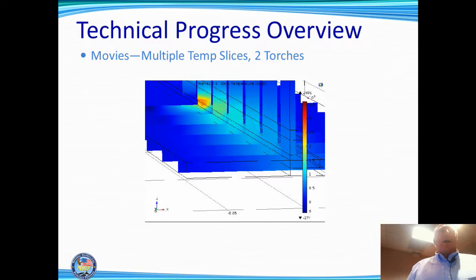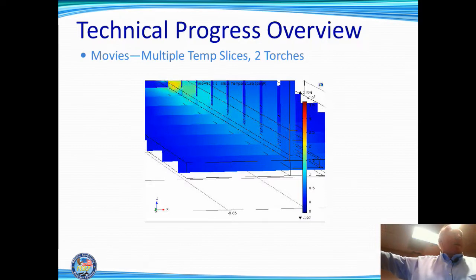So the fact that we have these models will help us a lot now as we move forward to looking at things like aluminum and other materials, because now instead of having to do 800 welds, which is how much we did, nobody had ever done this process before, so we didn't have any good rules of thumb. So this was a lot of welding engineering, try one thing and try another thing. So from now forward, though, we have these computer models which will help us zero in on one. And we just did one for Bollinger Shipbuilding, welding 4.5 millimeter material for them. And I think we came up with a good procedure in about 10 welds.